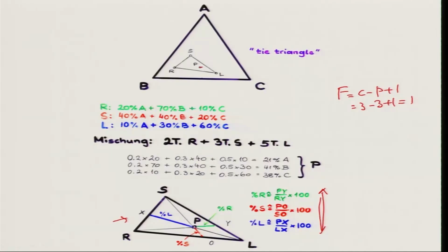When there are three phases, there are 6 independent composition variables, right? Why? Suppose you have liquid, alpha, beta as the three phases. The composition of liquid is represented by three elements: XA^L, XB^L, XC^L. Similarly, for alpha also XA^alpha, XB^alpha, XC^alpha, and for beta also XA^beta, XB^beta, XC^beta.